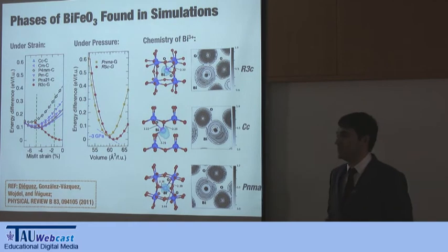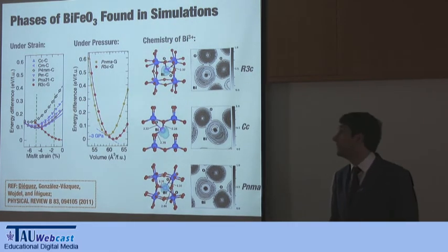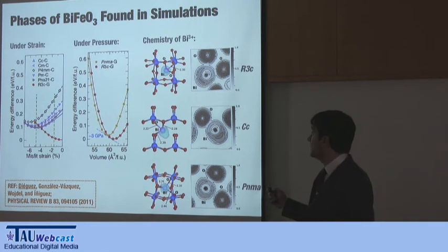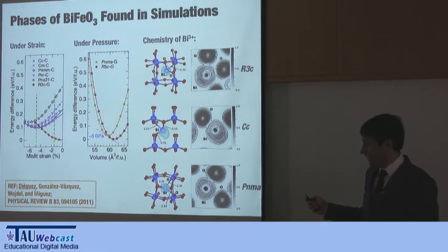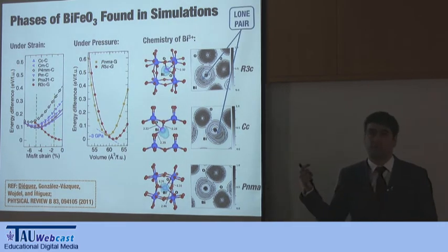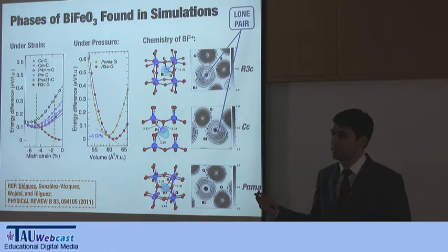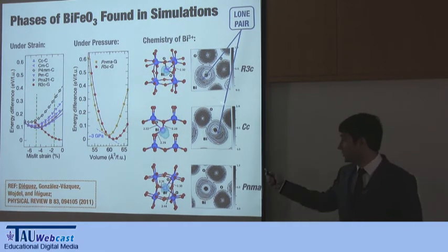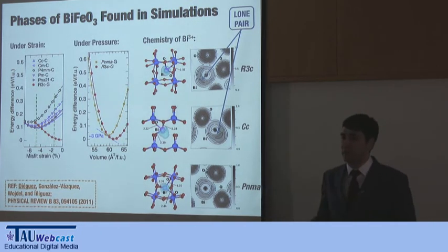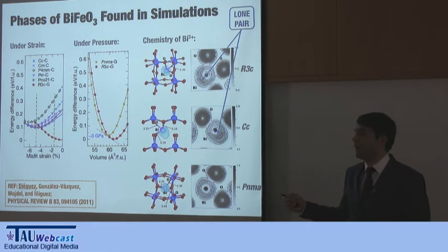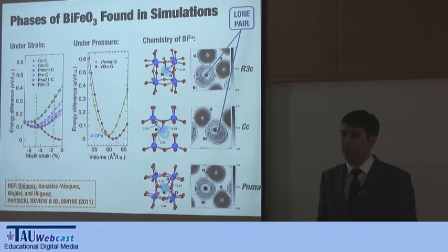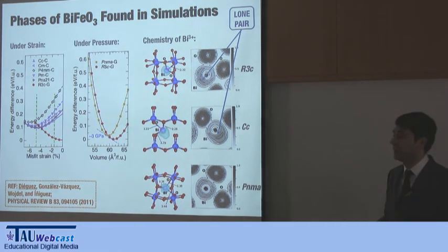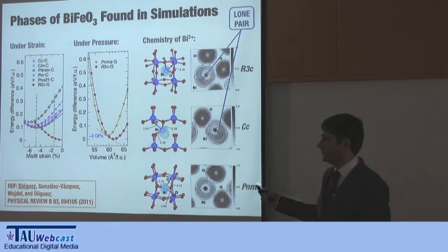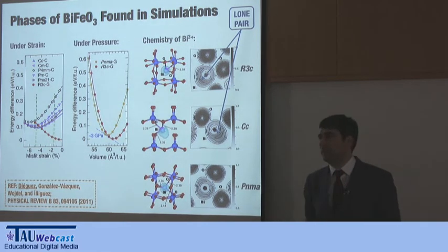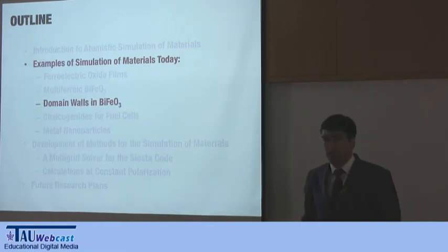Now, why does bismuth ferrite have so many metastable phases? The reason has to do with the lone pair of bismuth that we can see here. So bismuth 3+ has 2 electrons, 2 s electrons, that don't bind in many of these configurations. In some they do, but in many they don't bind to oxygens, and the system has to accommodate them. And basically, almost any direction in which the system accommodates the lone pair will give you a local minima. So there are many phases you can study, and this is the first study, kind of, that mapped consistently these phases that appear.